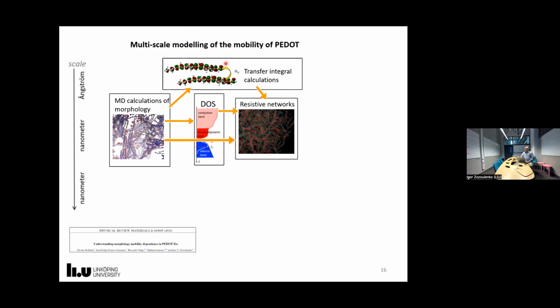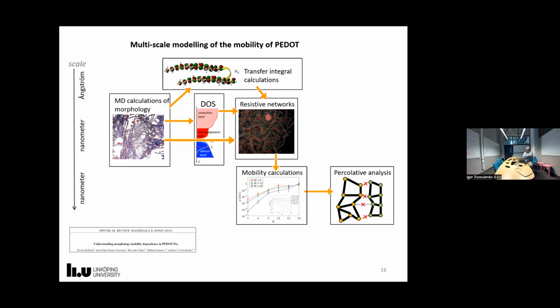Okay, and based on this, you construct so-called resistive networks. A resistive network describes these transport units, how the polaron jumps along the crystal. And then you do mobility calculations. Mobility calculations by themselves are very fine, but you have to understand them, so you need to analyze them using some kind of very transparent physical picture. This picture can be a so-called percolative analysis. So this is a general scheme of multi-scale transport calculation in conducting polymers.